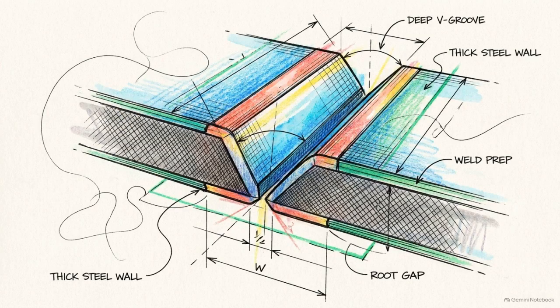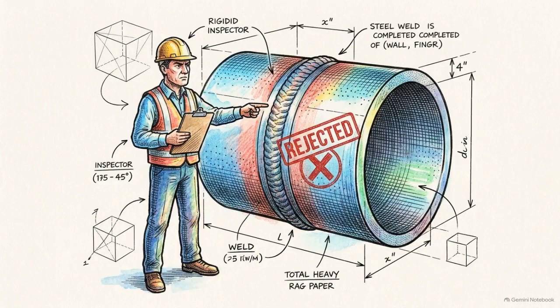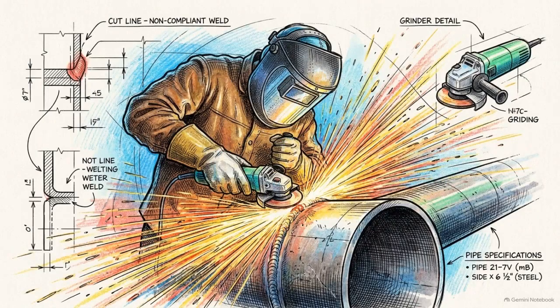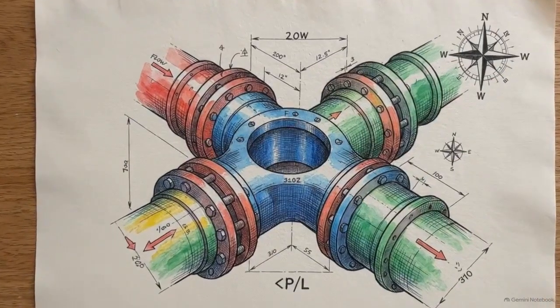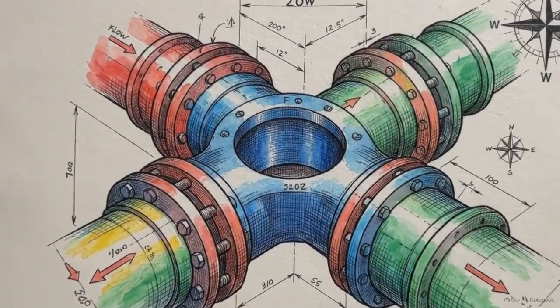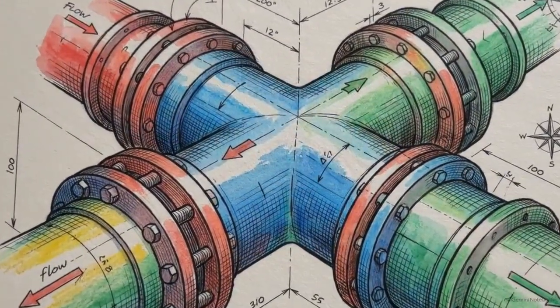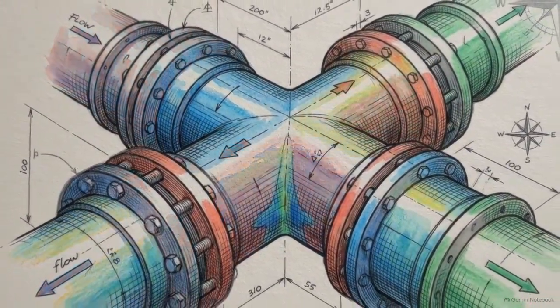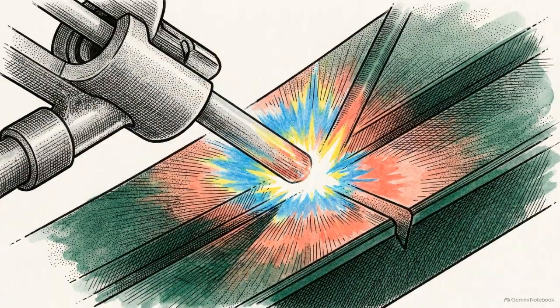The practical implications are significant. If this welder is assigned to a 1-inch thick joint, the work would be non-compliant, even if they hold a 6G certificate. Using a welder outside their qualified range results in mandatory cutouts and significant safety liabilities. The 6G test covers all welding positions, but the actual scope of work is still bound by the physical dimensions of the test coupon. Mastery of the code requires verifying these specific limits before the arc is struck.